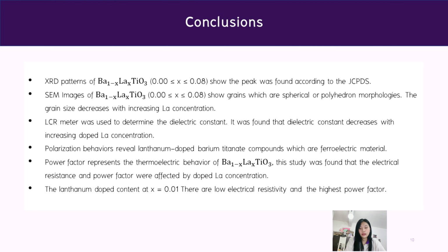Polarization behavior reveals that the lanthanum-doped barium titanate compounds are ferroelectric materials. Power factor represents the thermoelectric behavior of barium titanate doped with lanthanum. This study found that the electrical resistance and power factor were affected by doped lanthanum concentration. And finally, at lanthanum doping concentration x equals 0.01, there are low electrical resistivity and a high power factor.